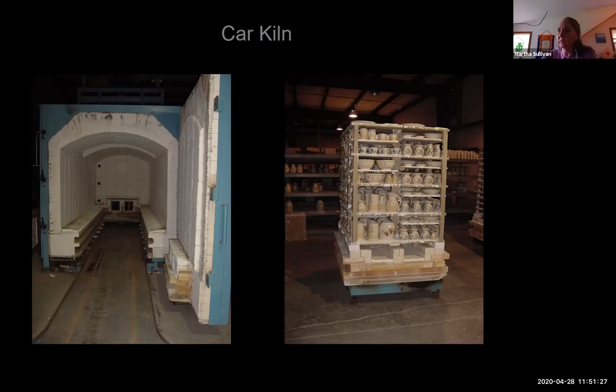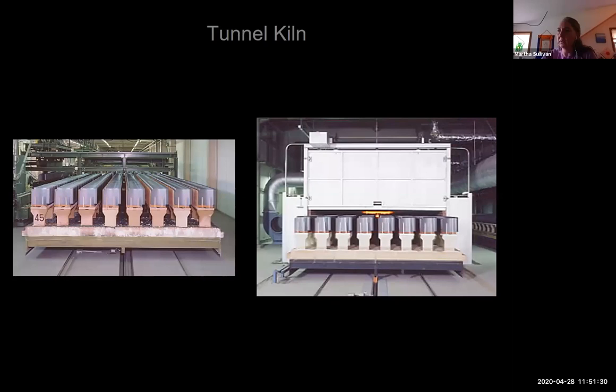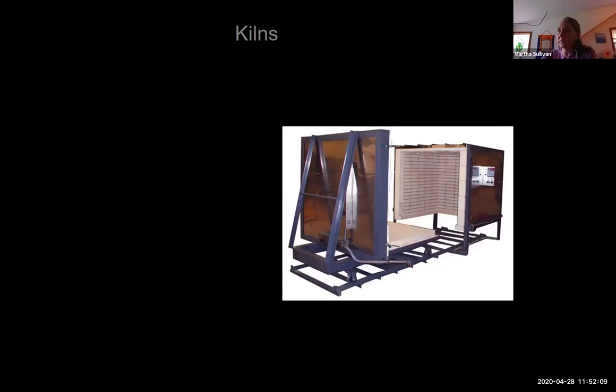Those car kilns can get enormous. So they can get as big as tunnels. So as long as Burchard Hall is, starting on one side and pushing all the way through. So in this tunnel kiln, you can see kind of on the right, there's this little tiny sliver of super, super hot. That's because that's so deep in the kiln. That's the 1-point perspective that you're looking at the width of the kiln. But with open ends, that thing runs 24/7. It's room temperature on the ends, and on the inside, it's probably 2,400 degrees, because those are like scientific refractory tiles. So again, just another little car kiln built on a track.